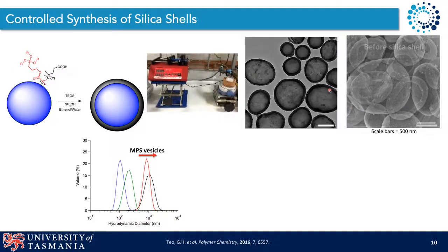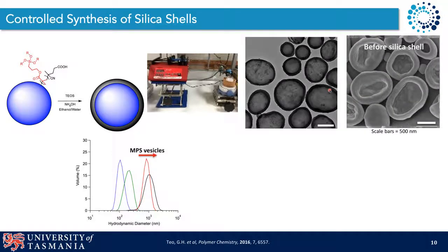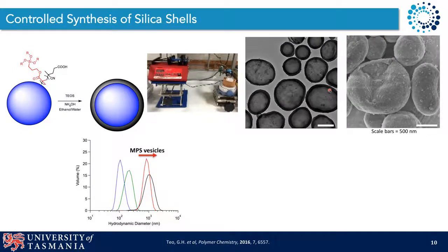If we quickly flip back to what our particles looked like prior to the growth of the silica shell, we can see that the vesicles have collapsed under the high vacuum conditions of the electron microscope. Compare that to when the silica shells are present, we have a greater retention of structural integrity due to the highly cross-linked nature of our now silica shell on the surface.